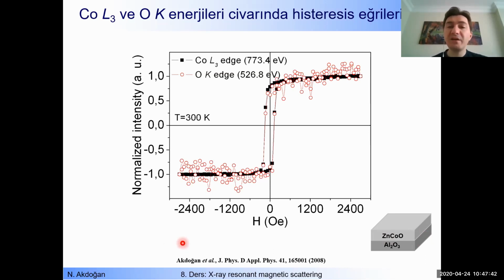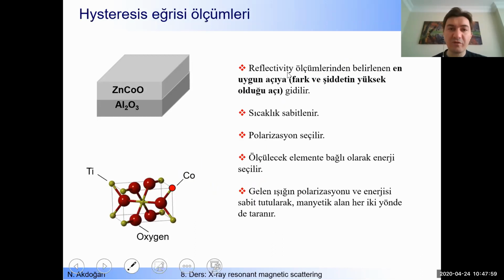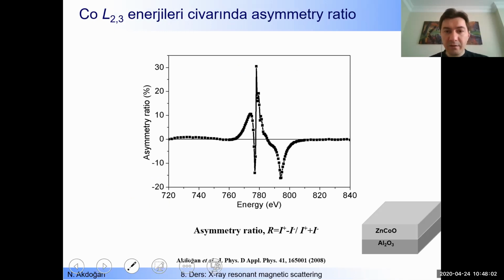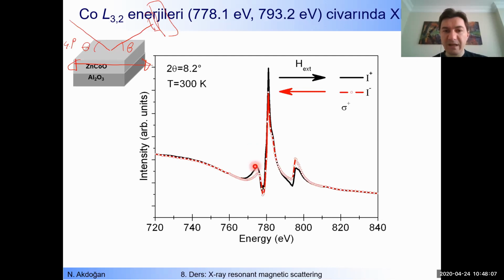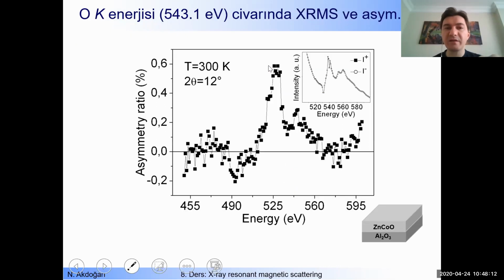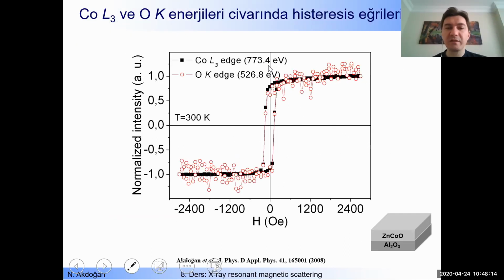So we scan the magnetic field. Here you see two curves, a black one and a red one. The black one is taken at the cobalt L3 energy, around 773.4 electron volt. Let me show you. Around this energy, somewhere here. You can also take somewhere here, but I'm showing the data taken at that energy.